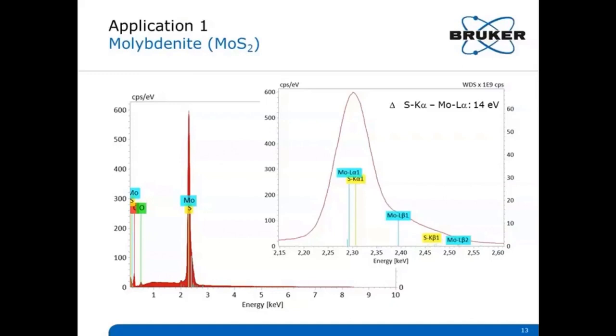On the left, you see the entire spectrum acquired at 10 kilovolts acceleration voltage, and in the right-hand side diagram, you see a blow-up of the region of interest with the interference of the molybdenum L lines with the sulfur K lines.